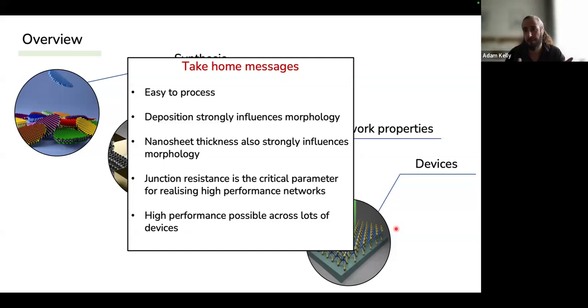So I presume the question there is, is it going to change the properties once it's deposited in the network? And usually what we want to do is actually get rid of the surfactant afterwards because we want the properties of the material, right? We don't really want to be changing their properties. So after you've deposited your network, there will be surfactant in there. What you can do then is just soak it in water overnight, for example, and you will remove basically all of the surfactant that way.